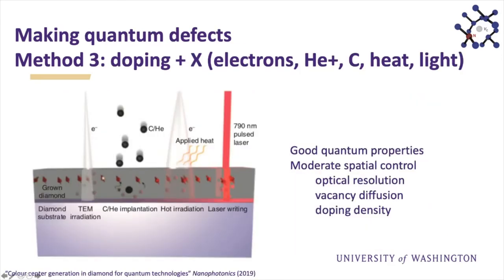And then another promising approach is to kind of combine the two things that we talked about. In this case, you dope, for example, in just a thin layer. So you just have the NV centers very close to the surface. And then you do something else to activate it or create the vacancies. So you're doping with nitrogen, and then you can irradiate with electrons to create the vacancies. You can implant with carbon or helium to create vacancies. You can actually just apply heat. So this is like a localized heat or heat with a laser to do the extra activation to create them. And these have very good quantum properties. There's moderate spatial control because you're limited by whatever the vacancy diffusion that you're creating.